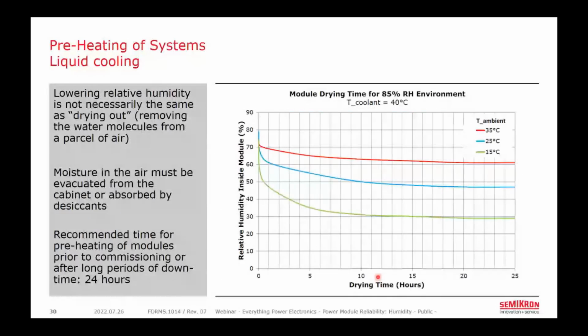So what we have here is a liquid-cooled power module that has been held in an 85% relative humidity environment until the relative humidity down at that chip level has reached 85%. So what I'm showing here is the results of an experiment very similar to what we showed earlier, except we're on a liquid-cooled heatsink. And this condition of having high relative humidity inside the module could be the situation if the power modules were transported through a high humidity environment, like a tropical environment by ship or whatnot, or if the power modules have been sitting unpowered for a long time in an outdoor environment. For example, in a wind turbine power converter that has undergone maintenance for some days and is not under operation.